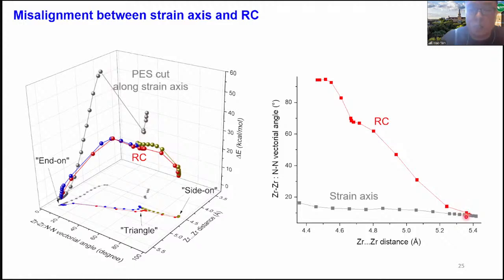So what we're seeing here is that pressure only pushes the zirconium distance closer together, but it does nothing to help with that rotation. In other words, the strain axis driven by the pressure in this case is misaligned with the reaction coordinate. And in this case, the pressure doesn't drive the reaction all the way to the product. You also need a thermal activation that assists the rotation of the dinitrogen in order for this reaction to happen.